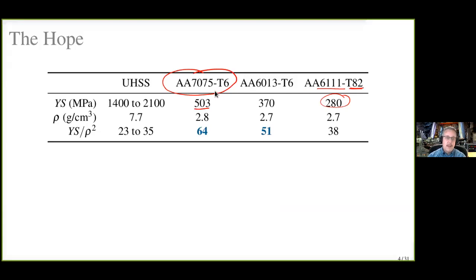What are they competing against? Well, they're competing against ultra high strength steels. So how do we compare these materials? Well, we look at yield strength here. We look at density. Now, if you have a simple tensile application of the material in a component, you could just divide yield strength by density and get a measure of how effective that material would be in that tensile application. For bending, though, we want to divide yield strength by the square of density. This is a good material selection criterion for bending.